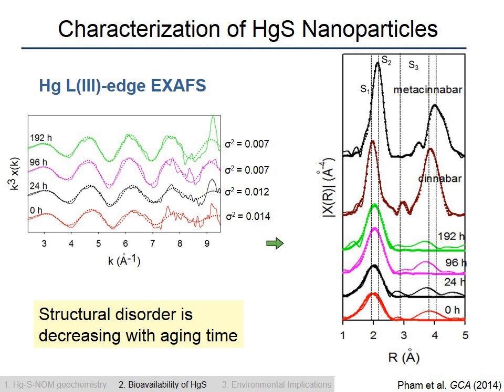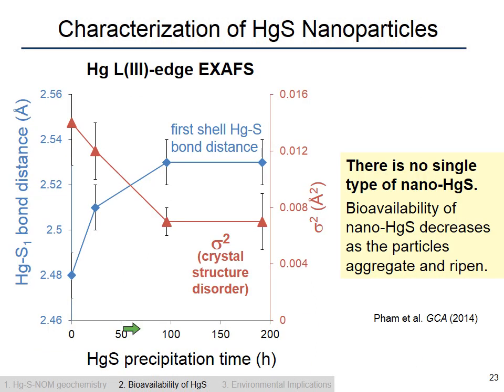So for a higher sigma squared, you have more disorder, or at least a more amorphous crystal structure. So what's happening here as particles age is not necessarily that their diameter is changing, but the structural disorder is changing. So with precipitation time, what we see is that the structural disorder in red is decreasing. So in other words, the crystals are ripening to more ordered structures. And we can see that the bond distance for this first mercury-sulfur bond is increasing and approaching the bond distance that you'd expect for crystalline metacinnabar.